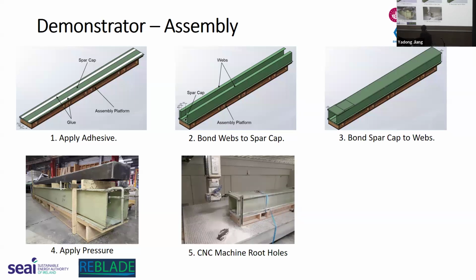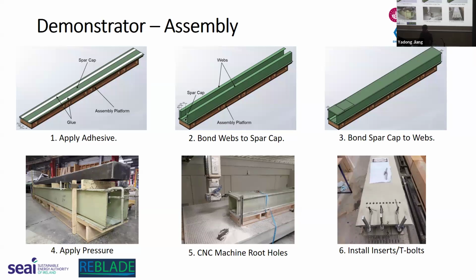Once it's all post-cured, it's ready for the CNC where the root holes are machined. That's to take the root inserts, the carrot-shaped root inserts or the T-bolts, and then installation of the inserts or T-bolts. You can see in this image here, in the bottom right, that the barrel nuts are on the piece of paper, and the bolts themselves are at the back. We put the barrel nuts into each of these holes, glue them in place, and then we pass the bolts through the holes at the root end, and they just screw into position.